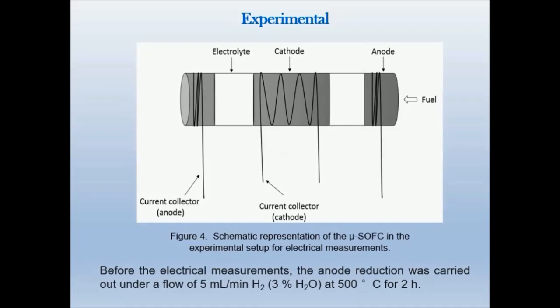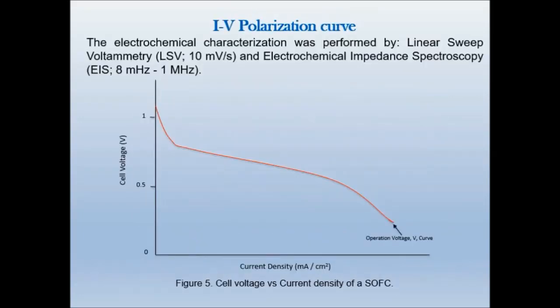Once the open circuit voltage is close to 1 volt and steady, linear sweep voltammetry followed by electrochemical impedance spectroscopic measurements were performed. From linear sweep voltammetry measurements, polarization curves were obtained. Electrochemical impedance spectroscopic measurements were made with an applied voltage signal with an amplitude of 10 millivolts in the range of frequency of 8 milliHertz to 1 megahertz. Regarding the results from linear sweep voltammetry, the voltage of the cell is plotted as a function of the current density to obtain polarization curves. The open circuit voltage is located at the null current density.